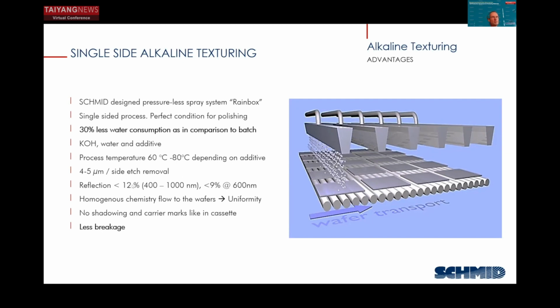Reflection is below 12%, and the range typically we have in the industry for this reflection at 600 nanometers is smaller than 9%. We have a very homogeneous chemistry flow to the wafer that supports a great uniformity, not only within wafer, but wafer to wafer uniformity. And with this, of course, we have no shadowing like you would have in a cassette, and as I pointed out earlier on, less breakage.